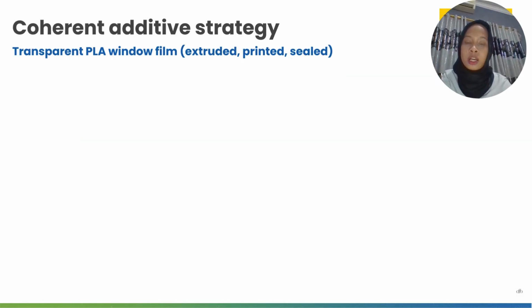Next, we're moving to the strategy, or coherent additive strategy, to overcome the failures. The first one, I divided into transparent PLA window film, which is extruded, printed, or sealed, and the tray. Film L: the goal is to pass EN 13432 plus keep clarity acceptable. The additive types are minimal AO, or hindered phenols and phosphite, at very low dose. Next is no HALS, with optional low-dose UVA only if needed. ESD is handled mostly by process control, which is ionizers, grounding, and optional very mild migratory antistatic.